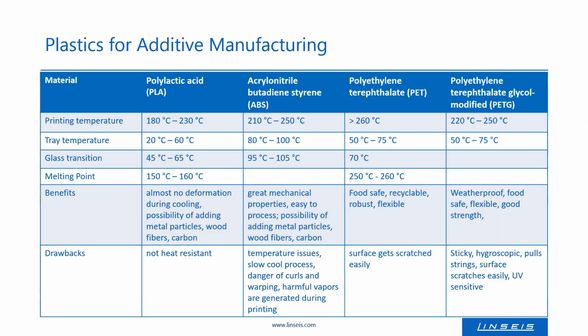And what is also a benefit of the material is that one can treat the printed material with acetone. By that, one achieves a smooth and shiny surface. For example, the bricks, which you could see in a picture some slides before, are also made out of ABS, and with the acetone treatment, one gets a shiny surface. ABS printed materials are, for example, also used in the interior of cars, toys, helmets, housings for electronics, or similar, since ABS has really great mechanical properties and is also rather easy to process and print in general.